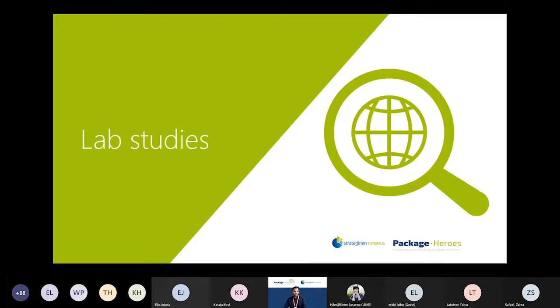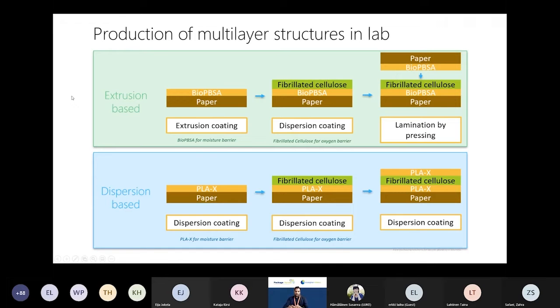And if we go to the lab studies part, so we can look at the structure development here, for example, for extrusion-based structure, where we were using this bio-PBSA because this film or coating was produced using extrusion technology. So we started with paper, extrusion coated that with bio-PBSA, and then we applied a dispersion coating of fibrillated cellulose on top of the bio-PBSA. And in the lab, of course, we could not take this to another extrusion coating step. So we basically laminated the same bio-PBSA coated paper upside down on that. And then this was characterized for barrier performance.